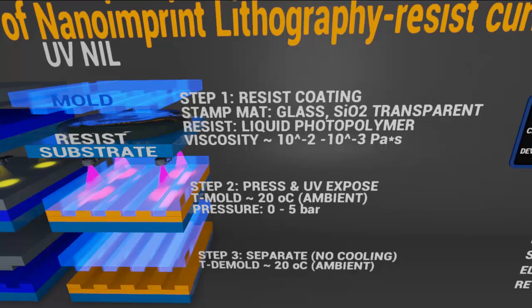The UV NIL process has several prominent advantages over the thermal NIL process, which include the capability of UV NIL to be conducted at room temperature without the need for elevated thermal imprinting, which helps eliminate issues resulting from thermal expansion variations between the mold, the substrates, and resist. In addition, the imprint process involves a less viscous liquid photoresist, allowing the process to be conducted at lower imprint pressure. The lower viscosity also allows the resist to fill the mold cavity in a shorter time, and the elimination of thermal cycles improves process throughput.